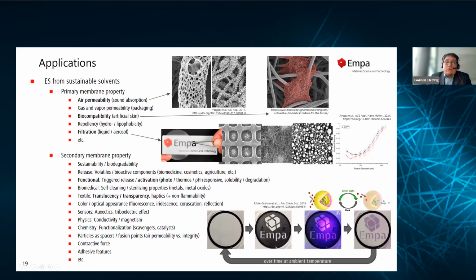The problem with that is if you increase the humidity too much, you simply get your solution to crash out directly on the wire. So that's not helping your spinning at all. So there are certain limits. You simply can't go to higher humidity, which is a particular problem with our setup, actually, because in winter we have relatively dry atmosphere, so we can spin all these non-humidity requiring solutions relatively nicely. And then in summer, when it gets so warm, we might not get below 20% or something humidity, and that means we already have some of these artifacts in there.